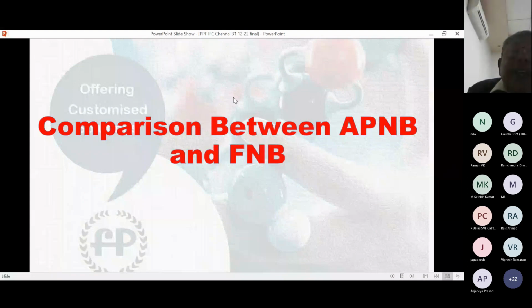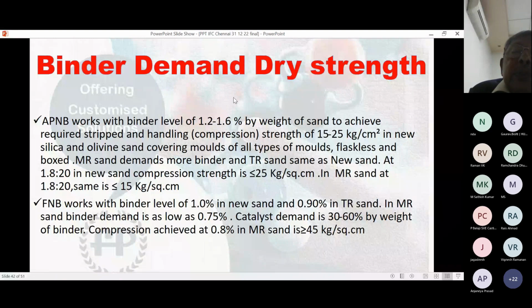APNB works with a binder level of 1.2 to 1.6%, which is much more demanding than Furan. Furan works at as low as 0.8% in reclaimed sand. Quality of reclaimed sand is also far better in the case of Furan compared to Alphaset. With all this, even with new sand at 2% addition, Alphaset sand rarely exceeds dry strength of 25 kg per centimeter square, whereas mechanically reclaimed sand using 0.8% Furan goes more than 45 kg per centimeter square dry strength.